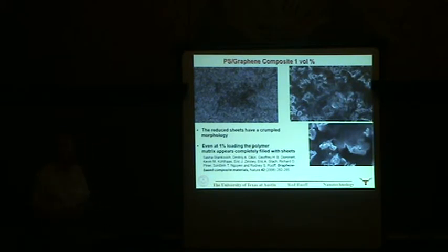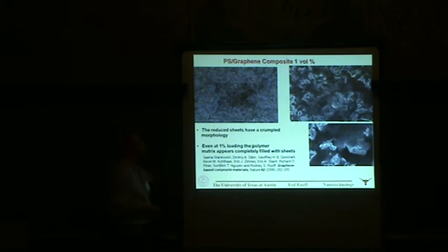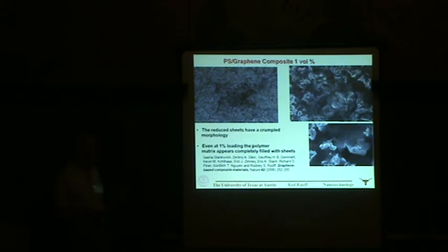Okay, so in a moment, I'm going to show you electrical percolation data that shows that this polymer matrix composite with polystyrene, which is of course electrically insulating, becomes electrically conductive at 0.1 volume percent loading with these platelets. Okay, now geometric percolation for pancake-shaped ellipsoids, for the oblate ellipsoids in terms of continuum mechanics and so on, this has been, of course, well studied, occurs also at 0.1 volume percent loading for an aspect ratio of 1,000. Okay, so pancake, oblate ellipsoid, 1,000 diameter, 1 unit thick.